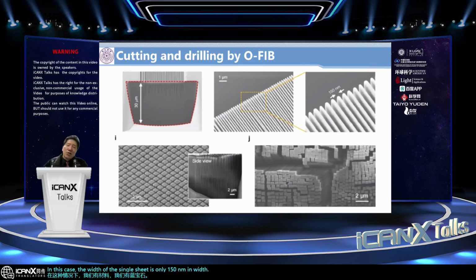You know, we can use other technology. If we use the FIB, we can cut to a smaller width, but we cannot cut very deep. But in our case, the width can be several tens of nanometers, and the depth can reach 1 millimeter. It means the aspect ratio is more than 10,000. So it is a very powerful, very useful technology.